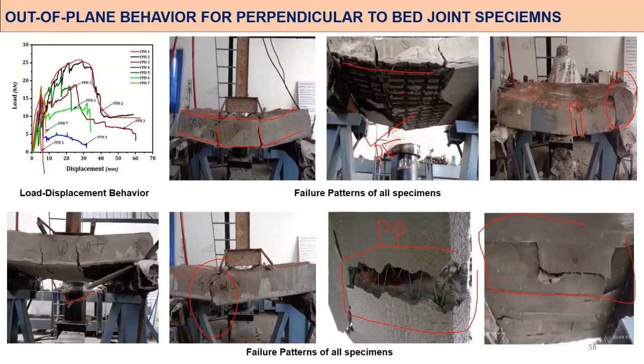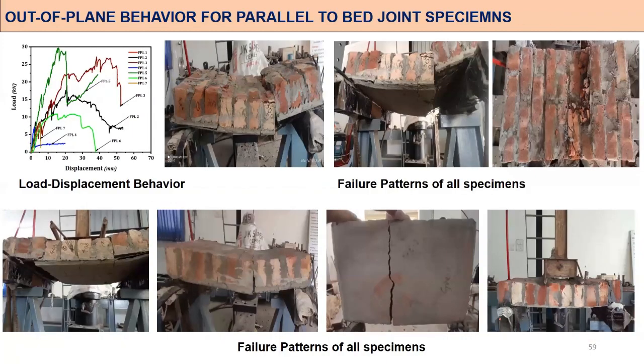At the same time, if you use a high modulus material, what will happen? Prior to reaching the yielding strain of your material, our brick will fail, because brick has a certain capacity which can't be matched with any kind of high strength material. That's why we have to choose the right material. Even when we choose textiles, we have to choose the right textile, and the number of layers matters.